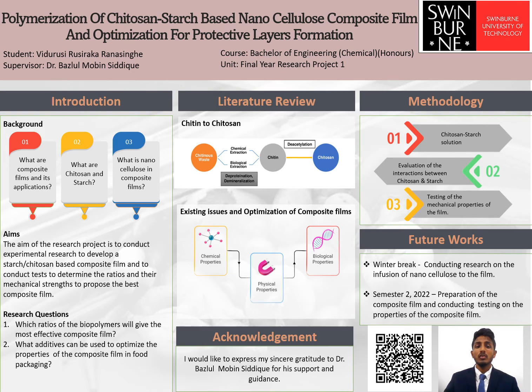After making separate solutions of chitosan and starch, a series of chitosan starch composite films can be prepared by mixing 100 milliliters of 2% chitosan solution with 4 different concentrations of starch solutions. To this solution, glycerin needs to be added as 25% of the total solid weight in solution. The purpose of adding glycerol was discussed earlier, therefore I will not be taking the time to discuss this again.